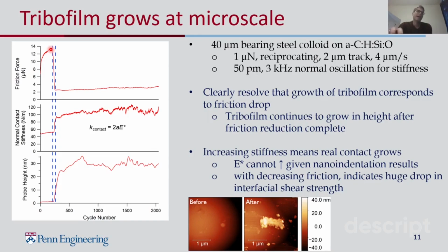But then there's a very, very dramatic thing that happens at about 300 cycles. There's a very dramatic drop in the friction force. And the drop in this friction force we attribute to the formation of a tribofilm based on 3 lines of evidence. The first one is that the normal contact stiffness changes dramatically at exactly the same time. And it actually goes up, not down. The fact that it goes up tells us that there's in fact a big increase in the real area of contact, because we know from other experiments that the tribofilm that forms is going to have a lower modulus than the starting material. So that would tend to drive down the contact stiffness, but in fact it goes up, indicating that the real area of contact is going up quite a bit.